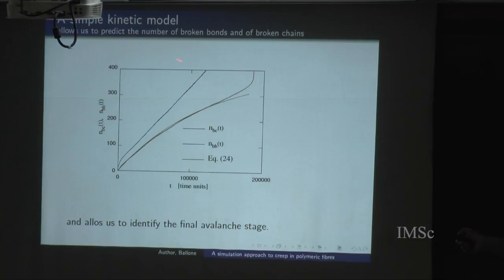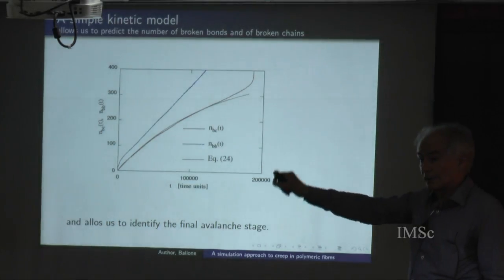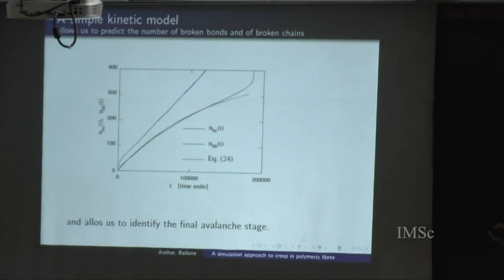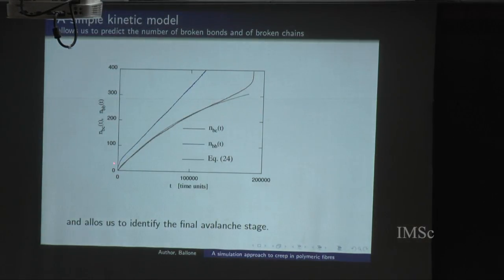So bond breaking is a rather rare event. Bond breaking is not the same as chain breaking, because you can break more than one bond on each chain. And so the two, at some point, split. We are able, by a kinetic model, to define the normal behavior, that is this line. When what we measure in the computation deviates from that, this is the avalanche.